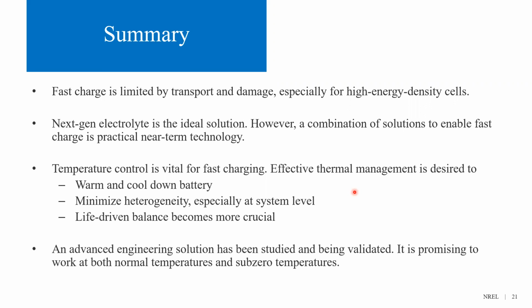Among the strategies we evaluated, temperature control is important for fast charging. Effective thermal management method should warm up and cool down battery efficiently. At system level, minimizing temperature heterogeneity is vital. Life-driven balancing may become necessary. Recently, we worked with AllCell to develop a thermal management solution based on phase change composite. It's promising this technology will work for both normal temperature and sub-zero temperatures.